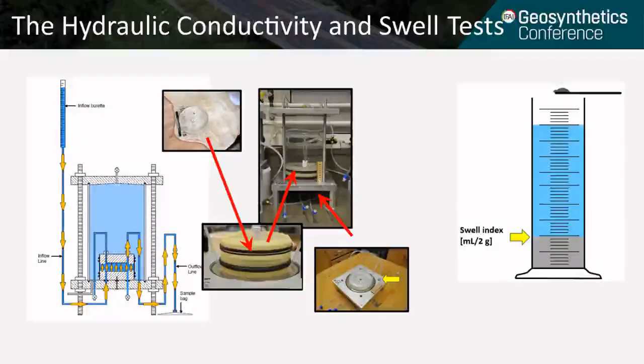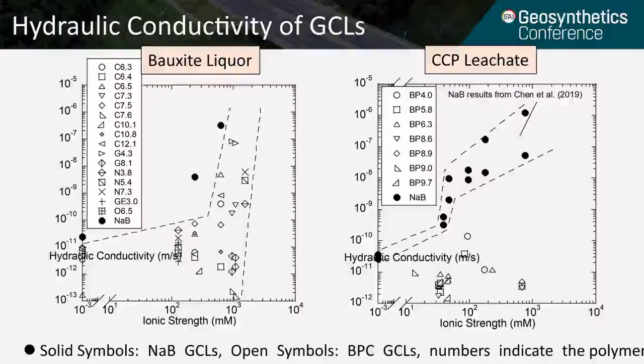So in this study, we used the traditional falling head flexible wall permeameters to evaluate the hydraulic conductivity of the BPC GCLs, and also we took out the bentonite to run swell index, and the microstructures were also analyzed by SEM with EDS. So here's the results of the hydraulic conductivity of BPC GCLs to bauxite liquor and CCP leachate.